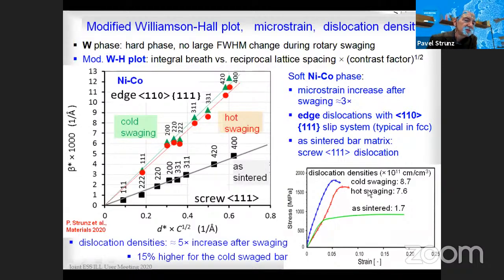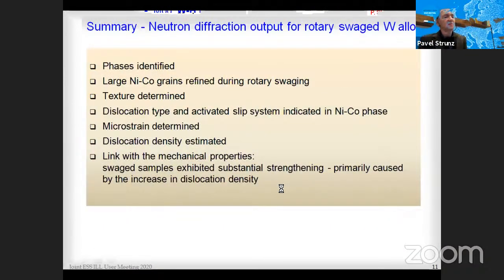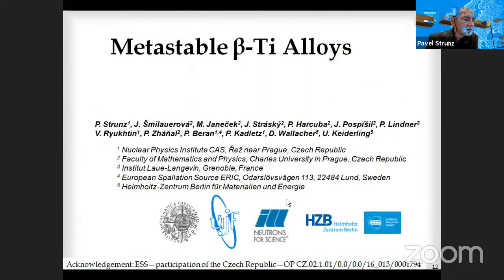And this means that the increase of dislocation density is the cause for the strengthening of the material, which is visible here. For cold swaged material, there is 15% higher dislocation density than for hot swaging, which also is in the same trend. Well, there is a list of sentences about the summary of this research. I will not repeat this because I said it a couple of seconds ago, and I will directly go to the second topic of my talk, which is metastable beta titanium alloys. Again, I list here the contributors to this research together with their affiliations.